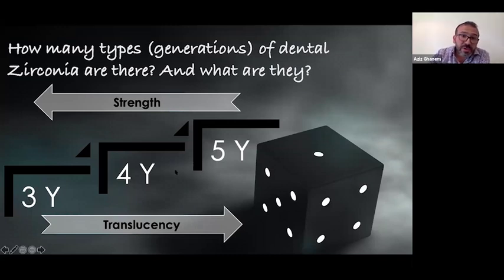So as we move from 3Y to 5Y, we will get more translucent zirconia. But if we move back, the high strength zirconia is the 3Y, and this is mainly because of the tetragonal phase. However, increasing the amount of dopant to 4Y resulted in about 25% of cubic zirconia, which has got a bigger grain and which allows more light transmission. And we'll talk in the next slide about that. And then you've got the 5Y, which has got about 50% cubic zirconia, and the rest about tetragonal.